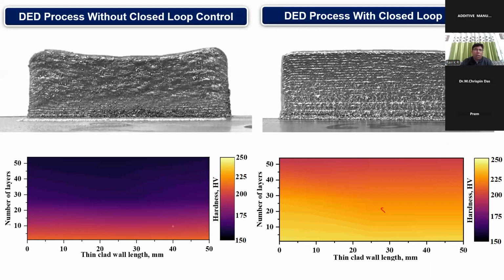If you look at the properties, we have taken the hardness as a function of number of layers. You can see the hardness varies, especially at the bottom of the layer, it's around 225 to 250 we are getting. On the top of the layer, we are getting 150 because of the defects in the part. On the other hand, we get a very uniform mechanical property when you do closed loop control.